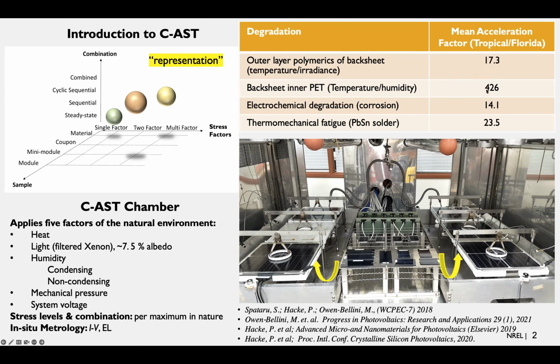So to keep that in perspective, though, for example, an 85 degrees C, 85% relative humidity test, such as IEC 61215, would lead to an acceleration factor of about 5,000, or just like 2 days in the chamber is roughly 20 years in the field. It's on that order. So even though this is high, this is somewhat a little bit more reasonable than what you would get at an 85 degrees C, 85% relative humidity test.